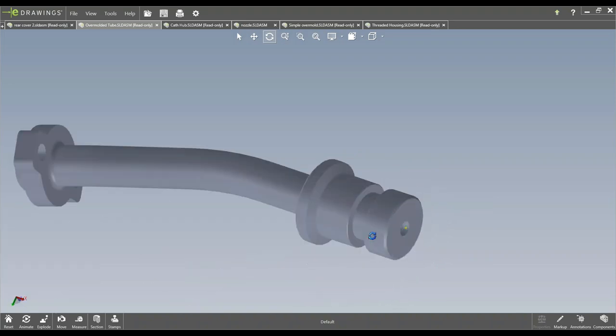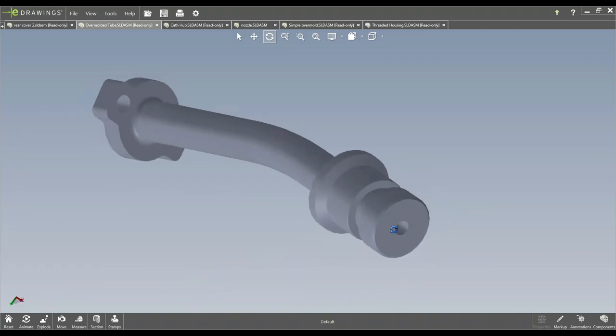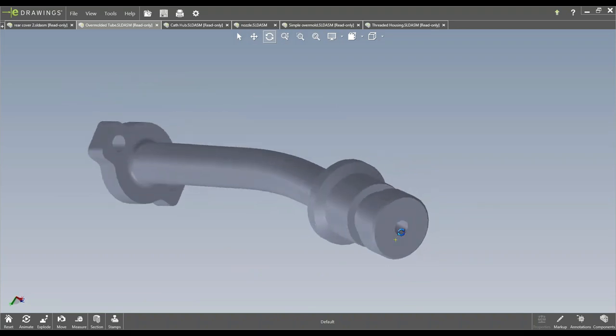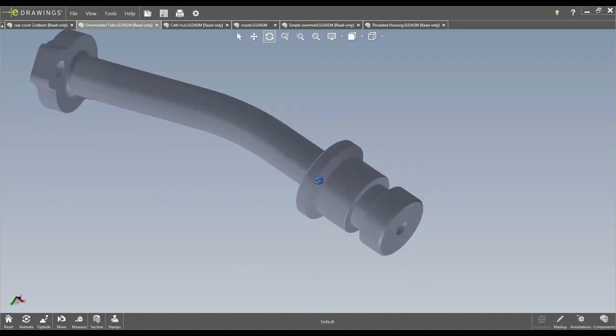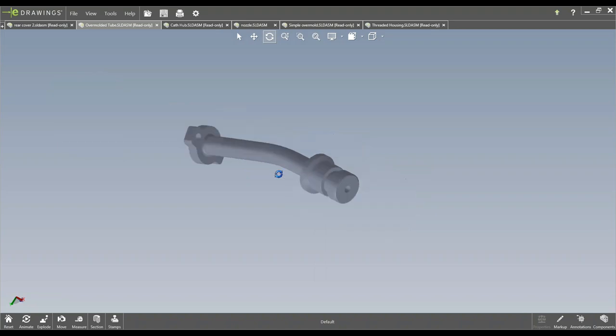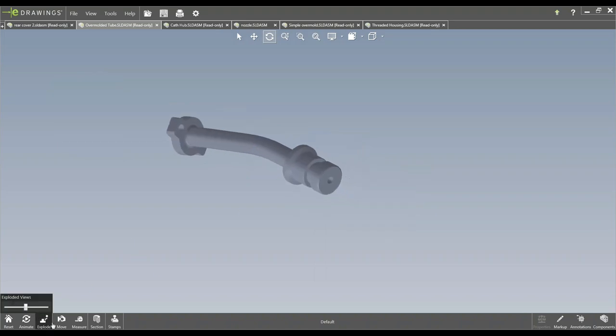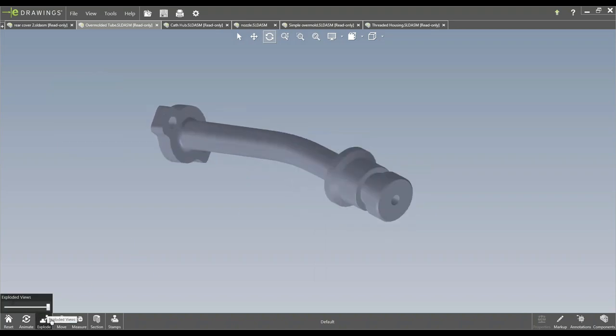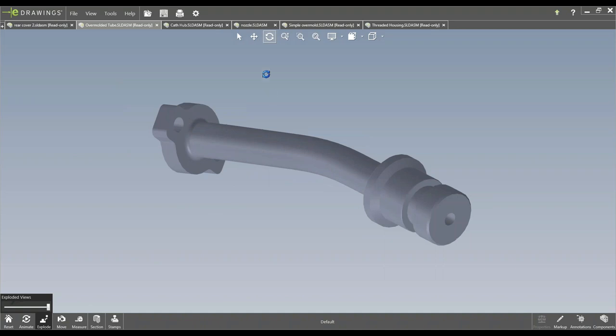So this is our first part here that we mold, and then we overmold this sort of thicker jacket around it. So what we have to do is actually mold in a 60 thousandths through hole throughout this entire part. Actually, this is the older version. And so we overmolded actually a rubber nylon tube throughout this part, and it's hard to control that tube.